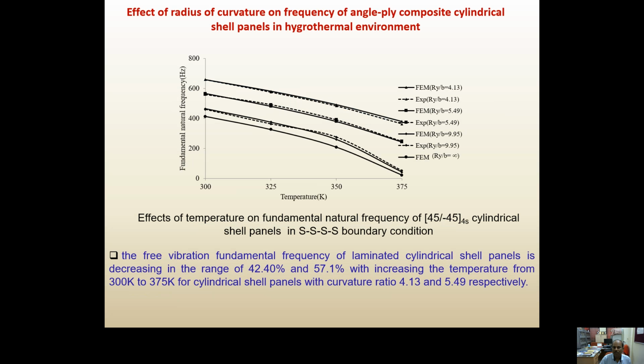Effect of radius of curvature on frequency of angle-ply composite shell panels in hygrothermal environment. So studies are also conducted, though this is a woven fiber. We have oriented the woven fiber in the direction of 45 degree and minus 45 degree, and fabricated the specimen and tested it. As you can see, this was a slightly different configuration, and the frequencies also reduced with the increase of temperature.